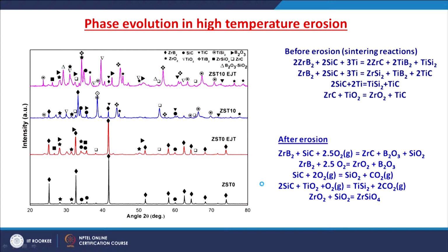A normal impact was selected because we know ceramic composites usually fracture to a larger extent at 90 degrees angle, and that leads to maximum wear. So, we selected these two, temperature and the angle. Now we can see the X-ray diffraction analysis for understanding the phase evolution in high temperature erosion. Here, ZS T0 means before erosion, just after sintering, and ZS T0 EJT means erosion tested. Similarly, ZS T10 before erosion and ZS T10 after erosion.